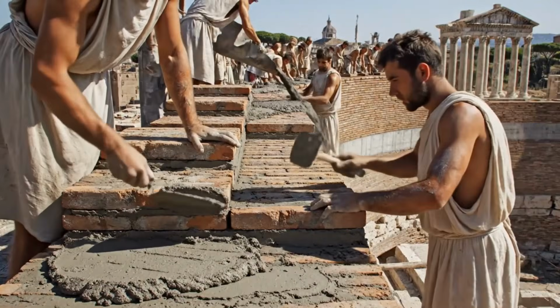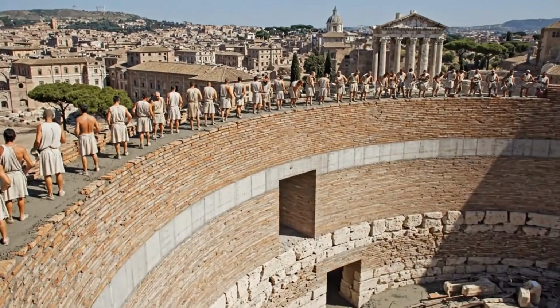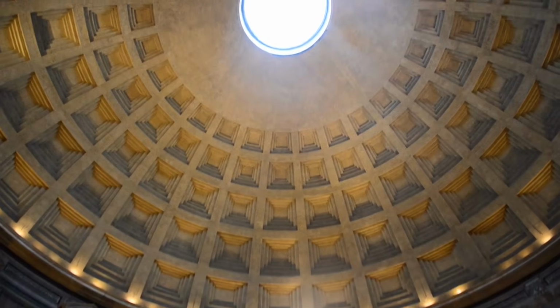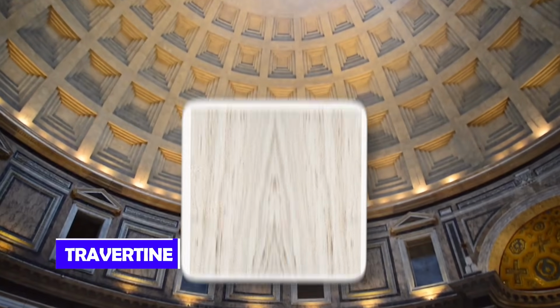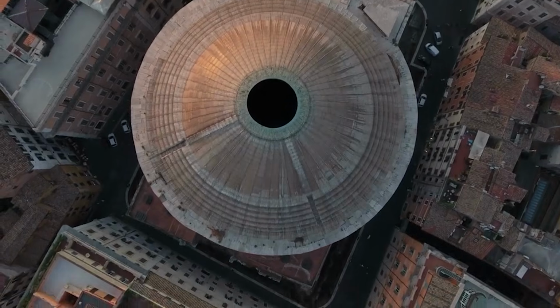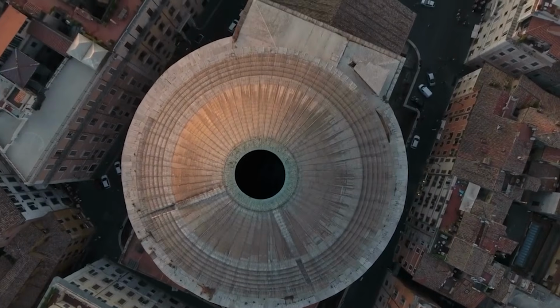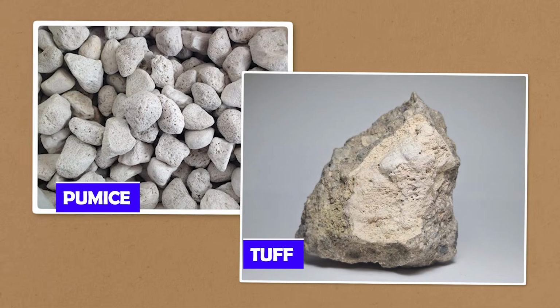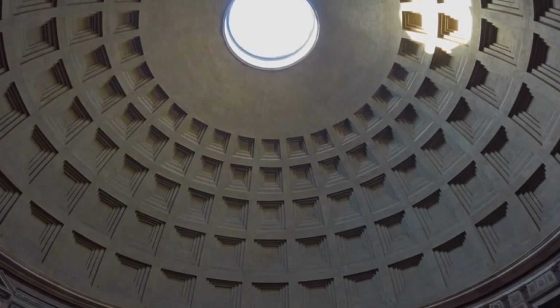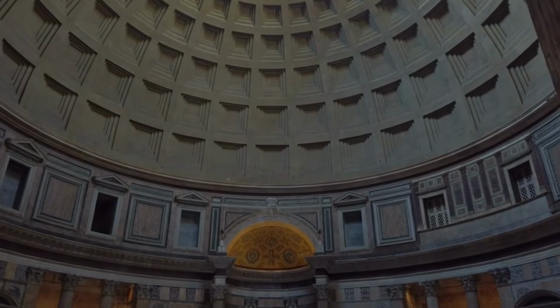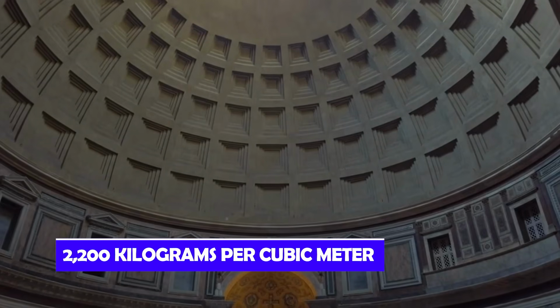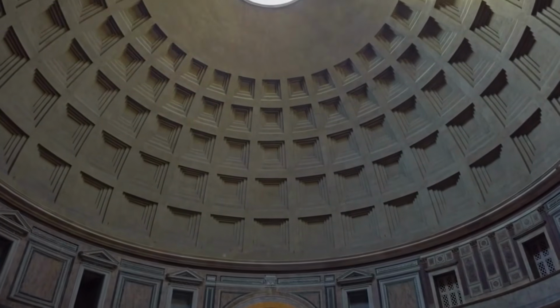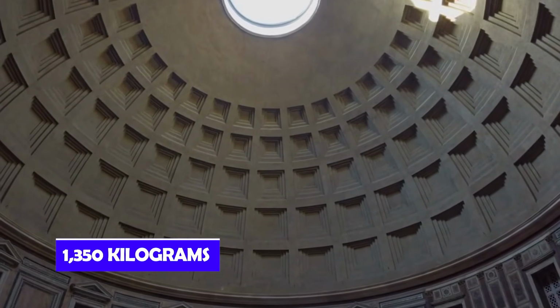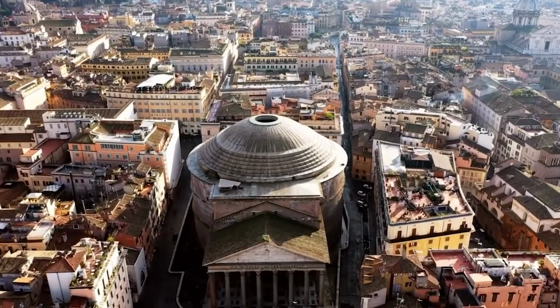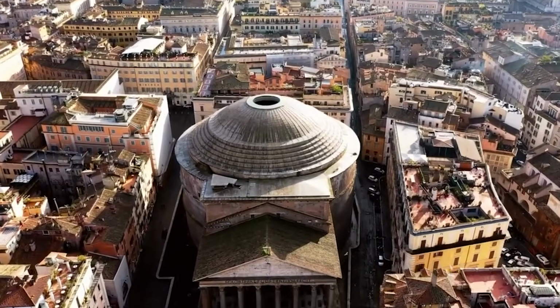Roman builders understood that the mixture could be customized depending on where it would be used. In the Pantheon dome, the aggregate near the base used heavy stones like travertine to support weight, while the upper layers incorporated lighter volcanic rocks such as pumice and tuff, gradually reducing the load as the dome rose higher. The density of the material changed from nearly 2,200 kilograms per cubic meter at the base to roughly 1,350 kilograms near the top. That gradient reduced stress on the structure while preserving strength.